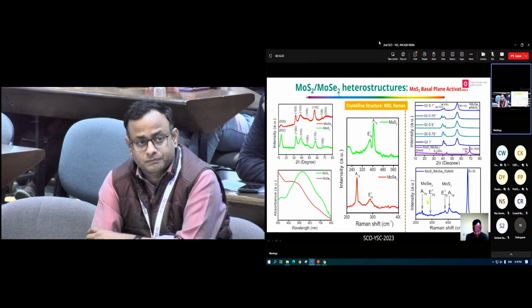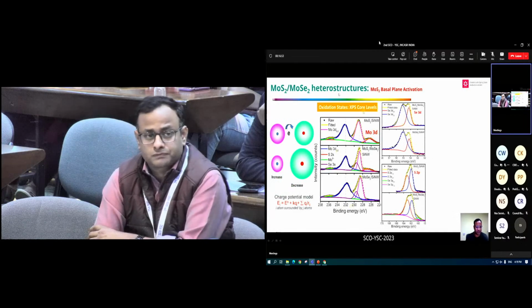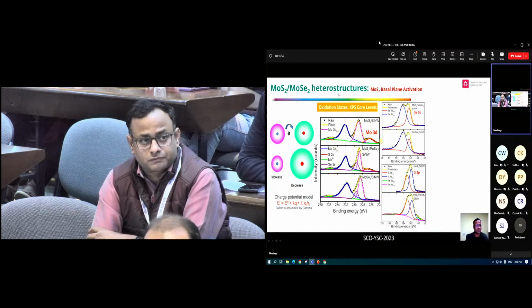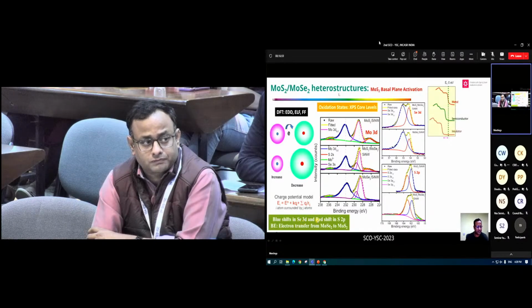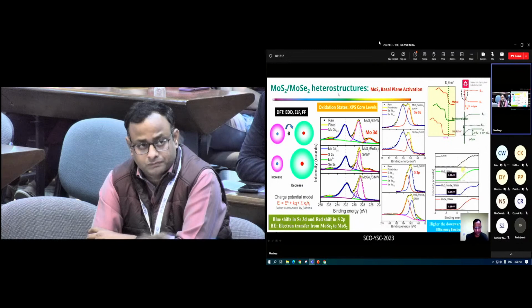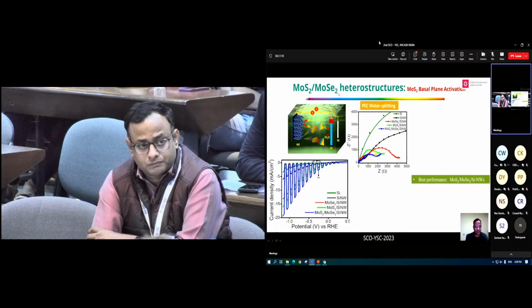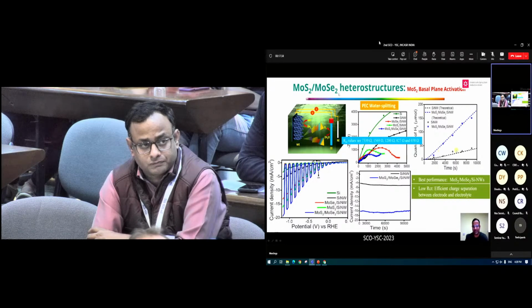After confirmation of the growth, we tried to understand their electron transport. When you look at the valence band and core level spectroscopy from XPS, it shows a red shift in selenium and a blue shift in sulfur, which tells you that the electron transfer is happening from MoSe2 to MoS2, and that was later proved by valence band spectroscopy. We have also done Mott-Schottky measurements. Once we take the MoS2 and MoSe2 heterostructure for photoelectrochemistry, the heterostructure with MoS2 on top gives the better performance, and then we tried to understand why. It gives lower charge resistance and higher hydrogen generation.